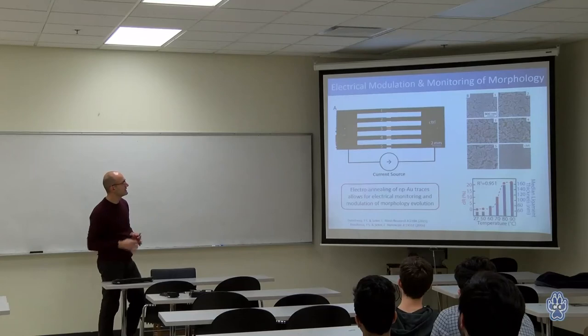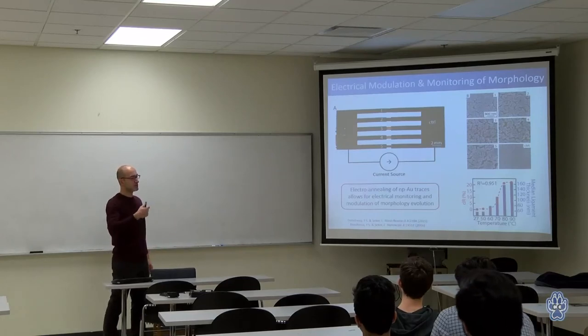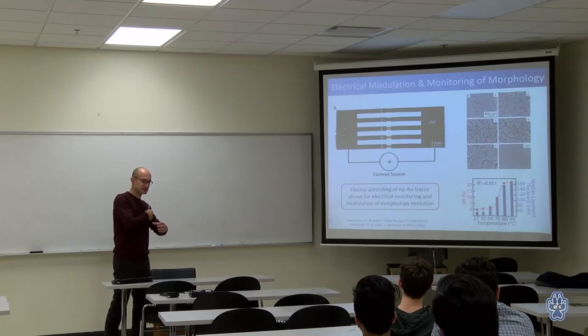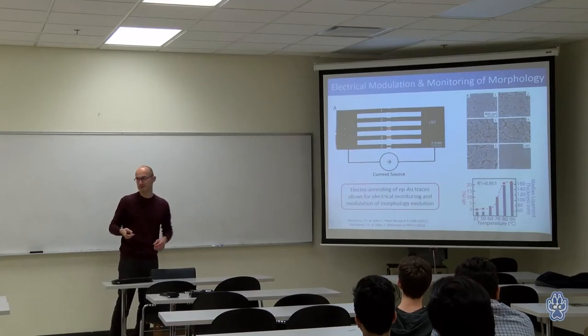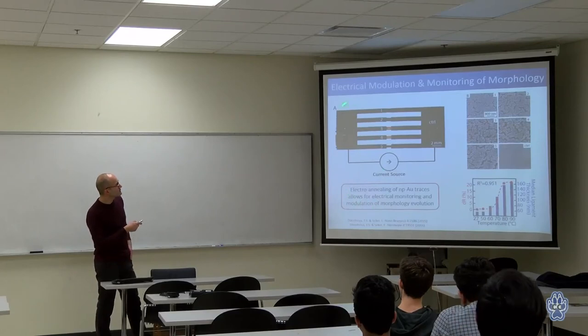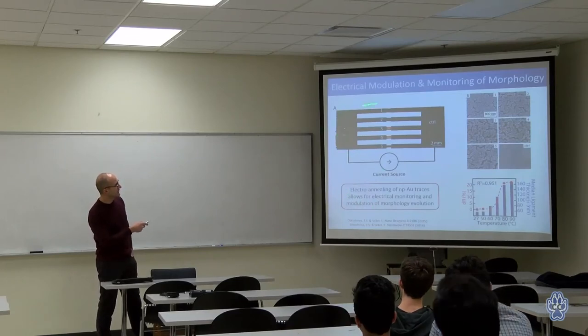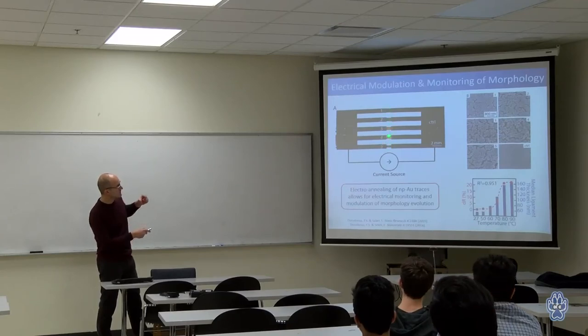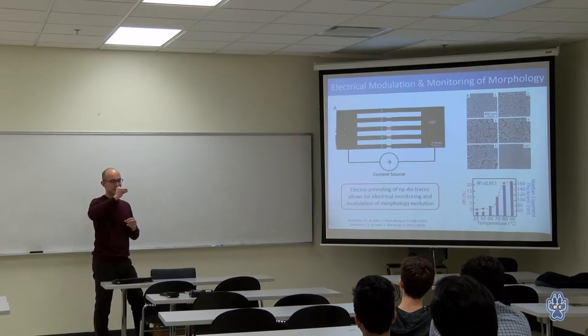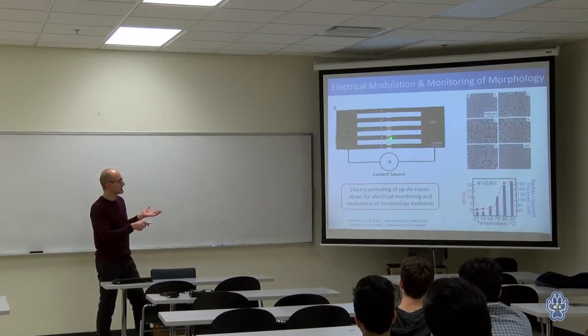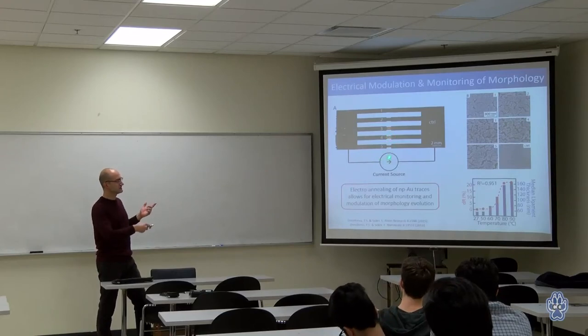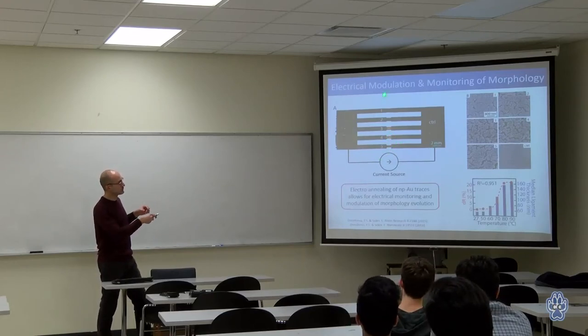So now, in high throughput, instead of testing one morphology at a time, in a chip you can test tens of morphologies at once, so you cut down the time to determining it. And for this one we use an electrical method, so you have electrodes patterned on glass, but we can change the geometry in the middle, putting constraints here, which increases your current density, so you have narrower regions, and it heats more, due to Joule heating from the higher current density. And it anneals differentially in different regions. So in one application of voltage and current flowing through these branches, you can end up with different morphologies on a single chip.